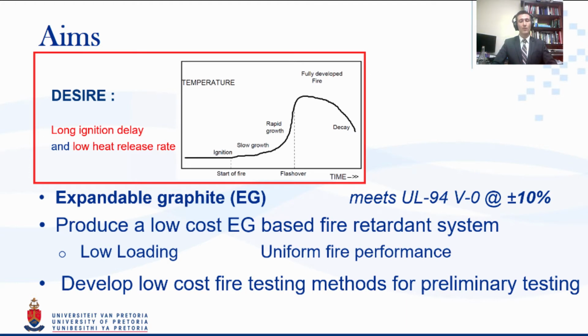But from below, there are very negative gravitational effects whereby the weight of the hanging expandable graphite strings actually pulls open more of the polymeric material, actually feeding the flame further. So in some cases, it actually had worse performance from below than unflame retardant polyethylene.